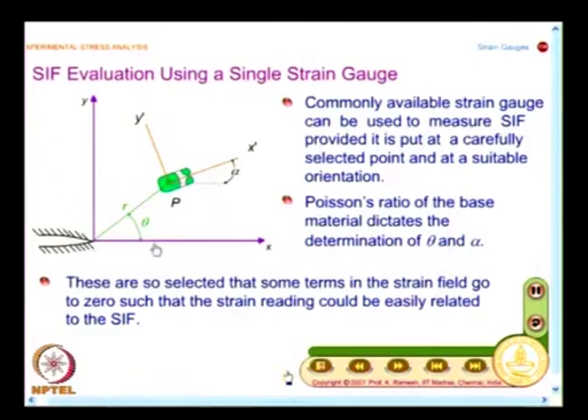You make a neat sketch of this diagram that illustrates how to use a single strain gauge for stress intensity factor measurement. I have this as the crack tip, and the crack tip is taken as the origin, and you locate the point P which is at an angle theta from the crack axis. At point P you measure strain along the direction alpha, that is very important. And I have already given you the clue, we have the Poisson's ratio of the base material which was used in designing the strain gauge. We will extrapolate those ideas and use the Poisson's ratio of the base material to find out appropriate values of theta and alpha,